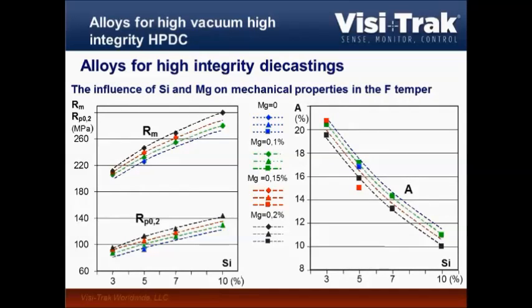Now if we look at what silicon and magnesium do, the main elements in this alloy family, we can clearly see the more silicon I add, the better my fluidity will be, but unfortunately the lower my ductility will be, but the higher my strength will be. Now, you won't determine your silicon level based on the strength and ductility you want to get. That might be taken into account, but mainly you want to determine the silicon level looking at the castability and fluidity in the alloy that you will need, and then adjust it with a magnesium content.